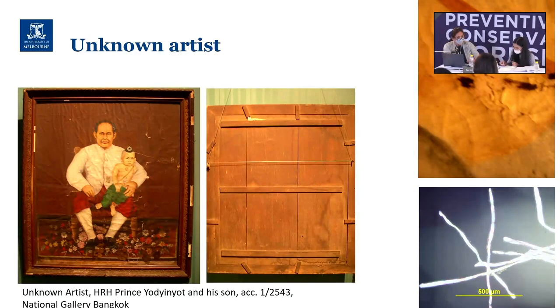And then if you have brittle materials exposed to a climate that has a high relative humidity and temperature, a whole range from very hot to cooler, and also high relative humidity changes as well, it means that they will not be able to move around very well and they will crack as a consequence. So often you see brittle materials producing these types of cracks.